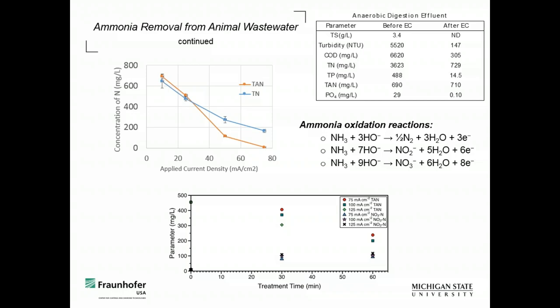And so as you can see, once we get up to 50 and 75, that's where we really can remove 100% of the ammonia. But as you can see, we've converted about 20% of it to nitrate. We did nitrite and nitrate measurements, and the remaining TN was exclusively nitrate, which is okay for this process and what they were doing because they were using it for irrigation water, so that was okay. Here are some model reactions.